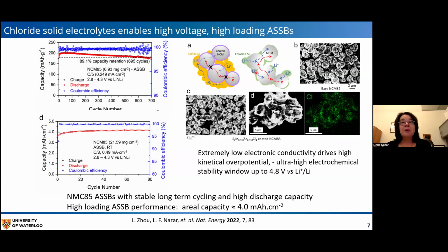And the lithium from the electrolyte then feeds into the system, as shown by the blue arrows, through this patchy type coating. And as I said, the low electronic conductivity of this electrolyte, shown here in green, renders it somewhat resistant to any electrochemical oxidation. And so these are all of the important qualities.